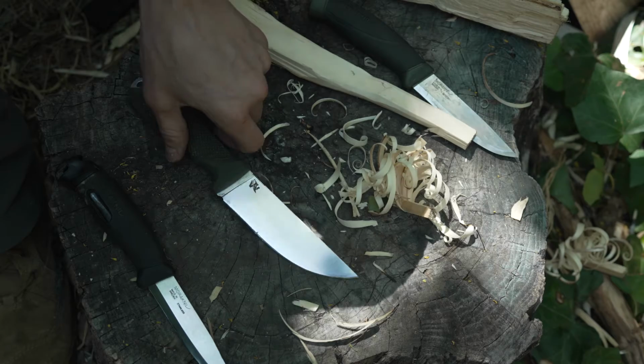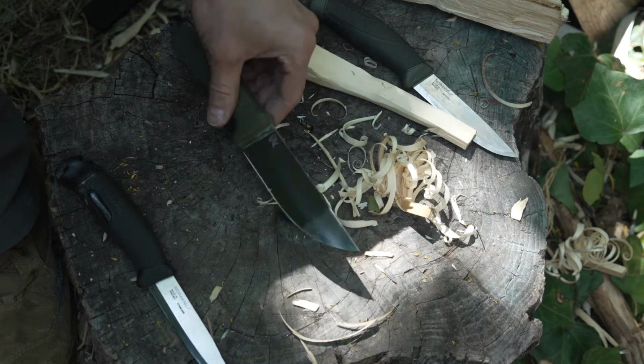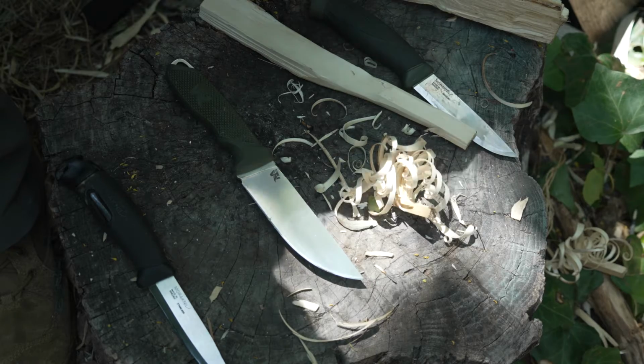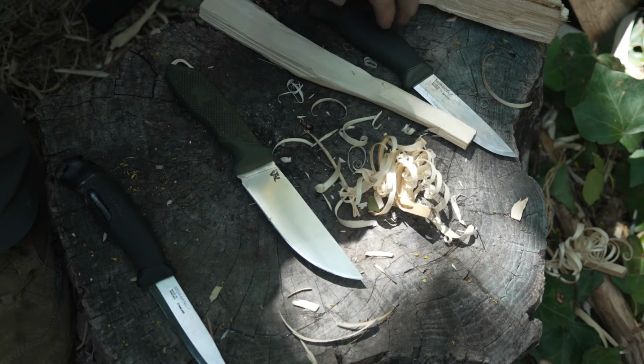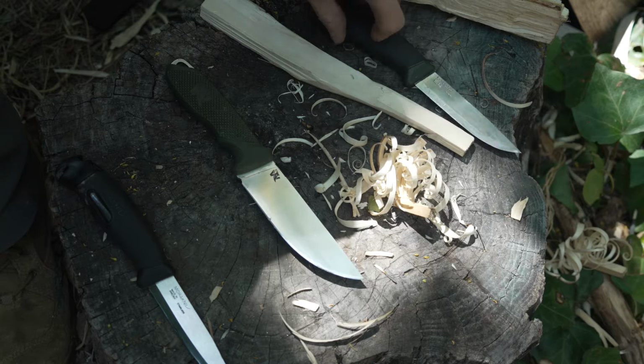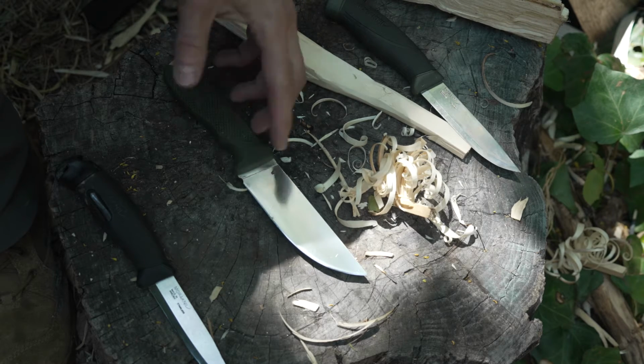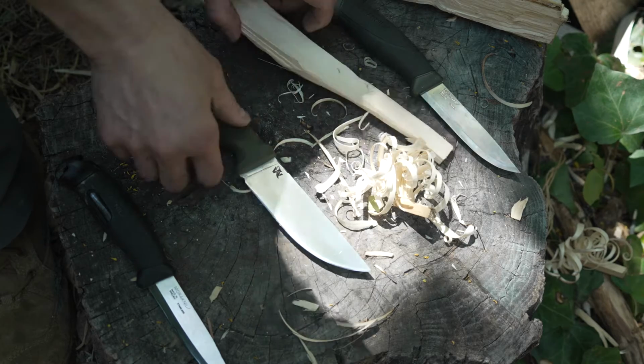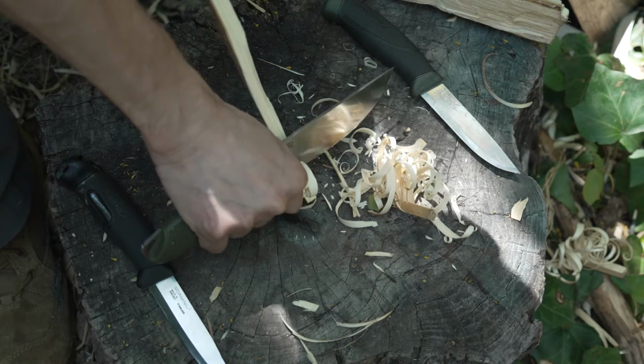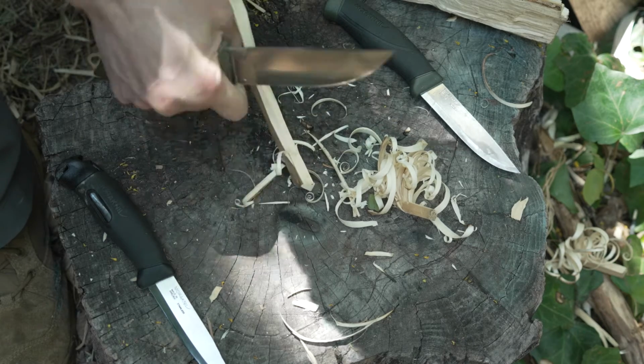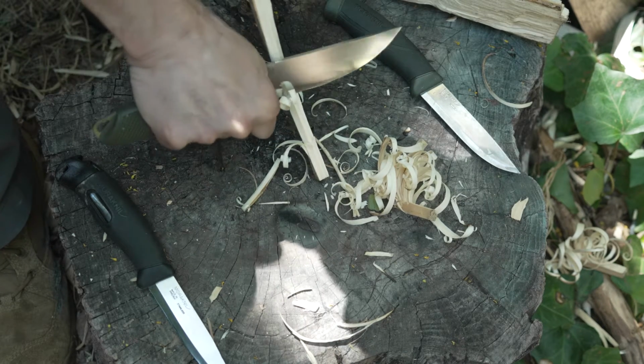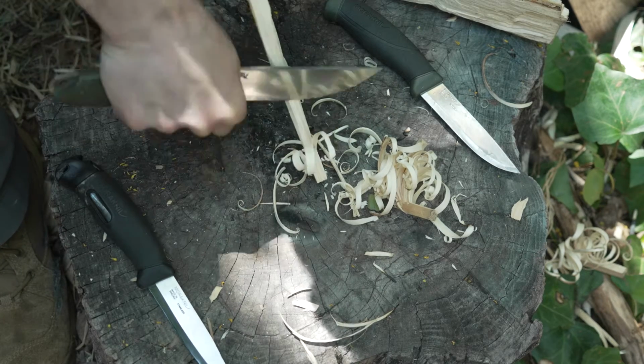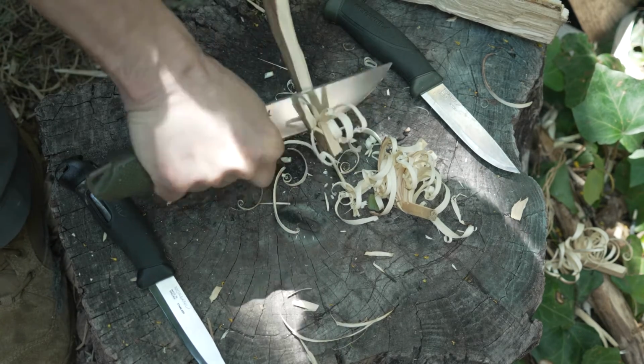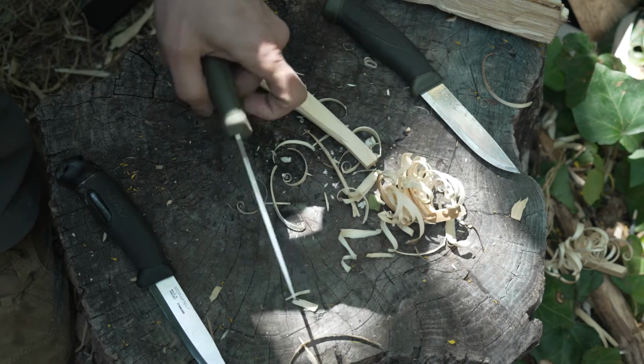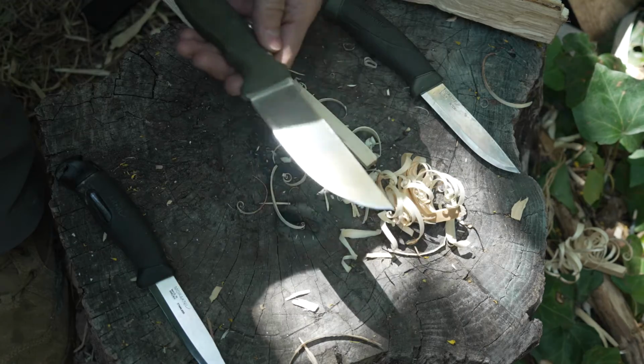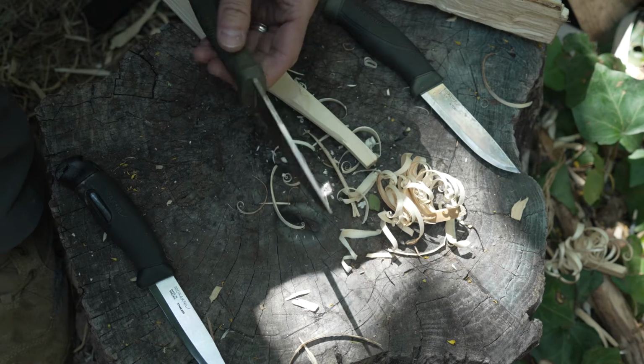My preference is D2. This is a stainless version of tool steel, so it also has vanadium in it, tungsten in it, small amounts of it, chromium in it, and it can have every bit as much carbon as a carbon steel blade, but those added components, added metals, increase the toughness and wear resistance of the blade, so it's going to keep an edge longer. It will affect the brittleness. Like everything in metallurgy is a give and take, so it will affect the durability of the steel, the ability for the steel to take a beating. And so if you really want a knife to baton with, to abuse, you may steer clear of tool steels.